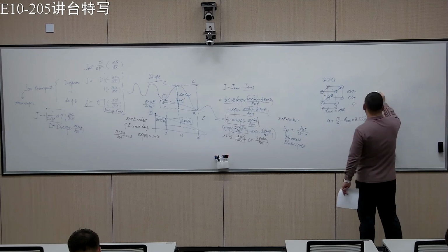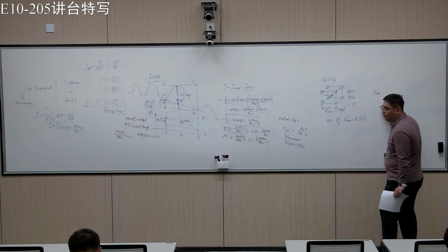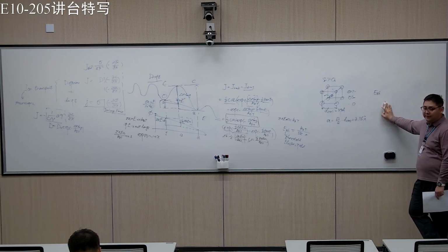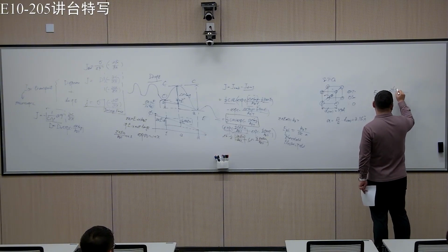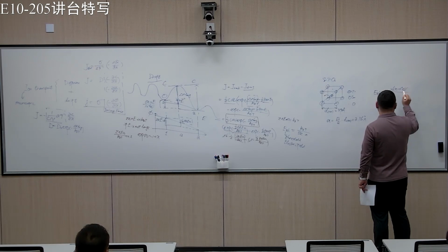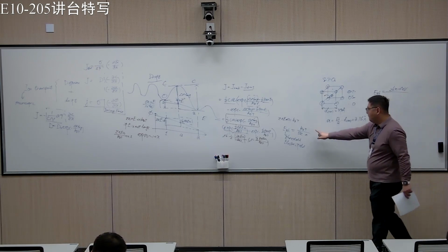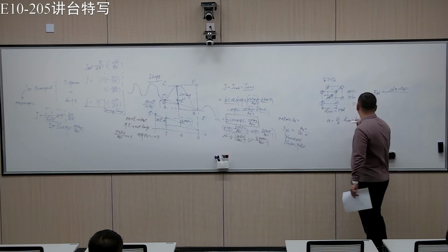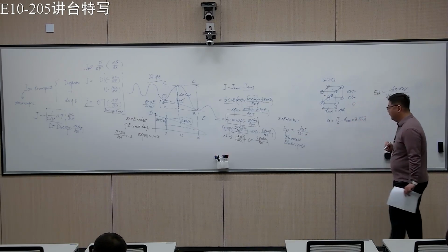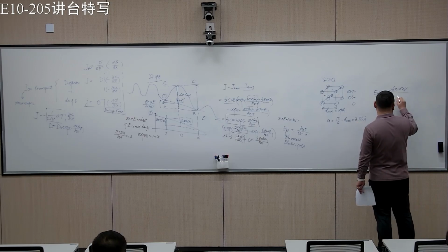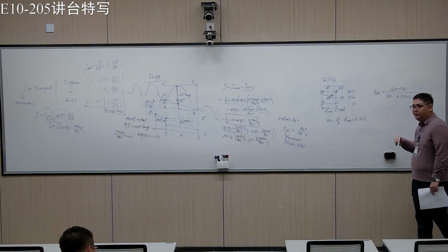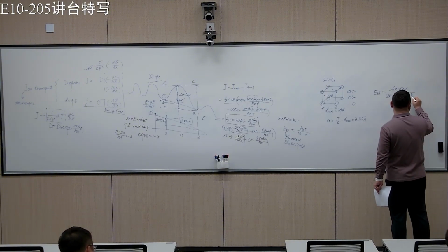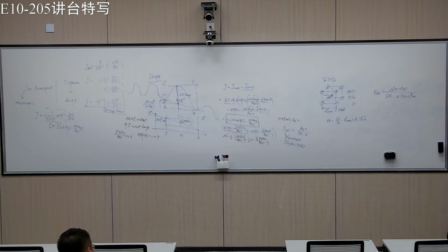Then if we want to change the diffusivity of oxygen in strontium titanate, even at room temperature, let's say 26 times 10 to the minus 3 electron volt for the KBT. And we know that oxygen has 2 electrons, right? Then A is 2.76 times 10 to the minus 10 meters. Because it's angstrom, let's say I want to convert to centimeters. So I get something like this. Okay. All right.